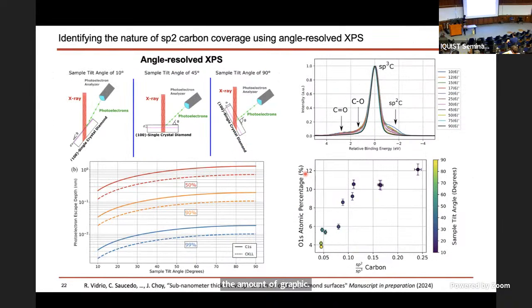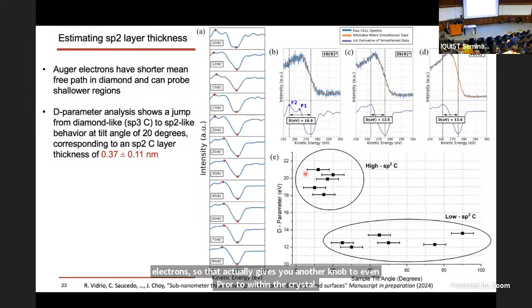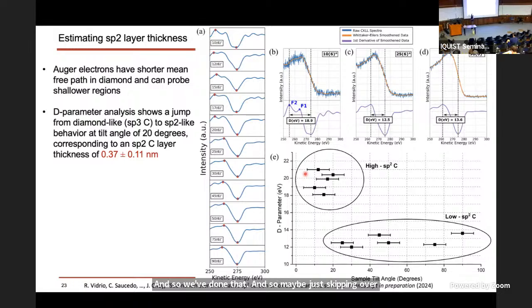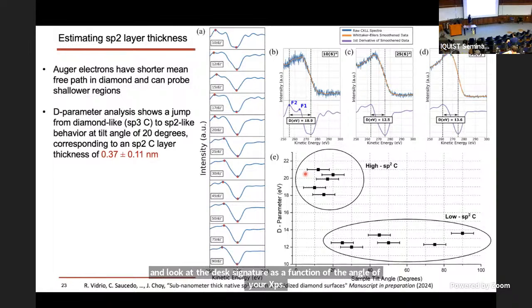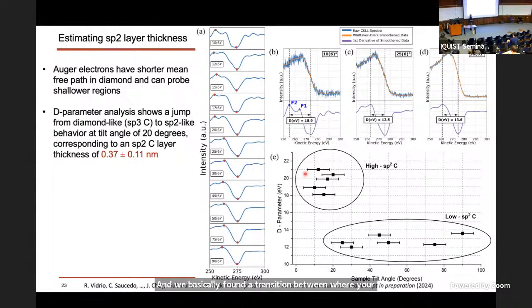And then another knob that we use is the fact that you can look at different types of photoelectrons. We can look at photoelectrons from the core electrons, so the C1s. You can also look at the Auger electrons. And the nice thing about the Auger electrons is that the escape depth is much lower than the core electrons. So that gives you another knob to probe even shallower within the crystal. And so we've done that. And maybe just skipping over this particular detail, we look at the Auger electron and look at the signature as a function of the angle of your XPS. And we basically found a transition between where you're predominantly diamond-like to where you are predominantly graphitic-like, or sp2-like. And that allows us to quantify the thickness of this sp2 layer, which is just a couple of monolayers. So it's about 0.4 nanometers.